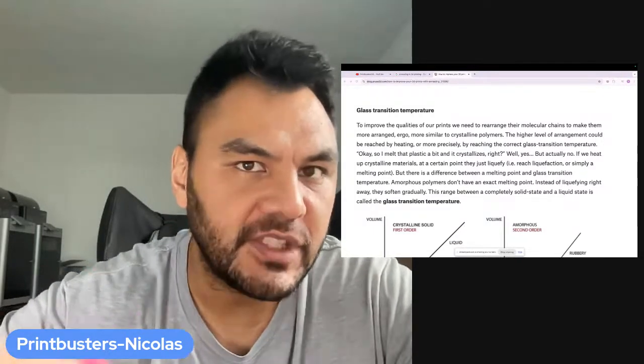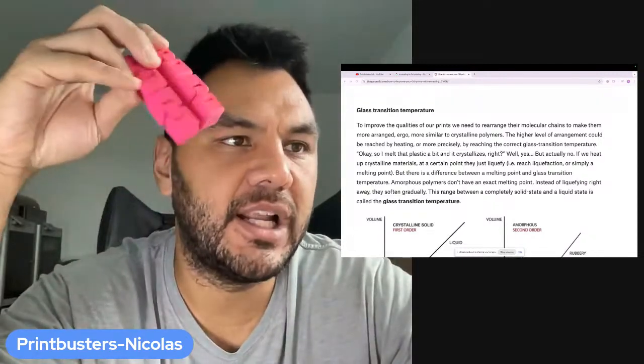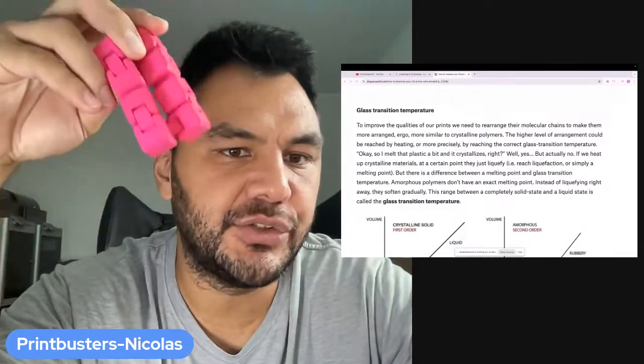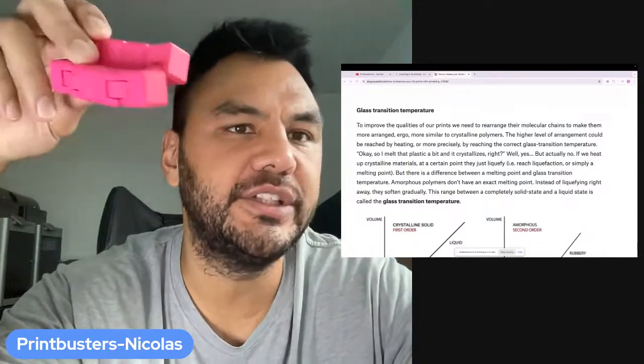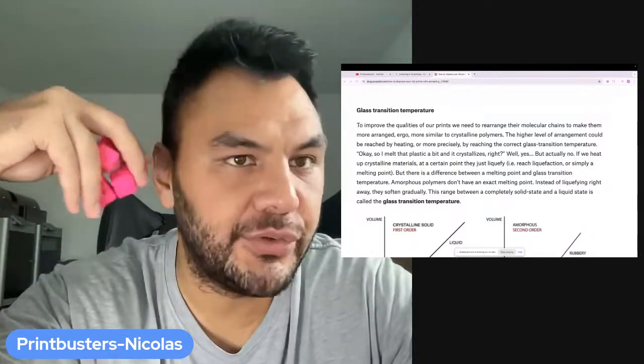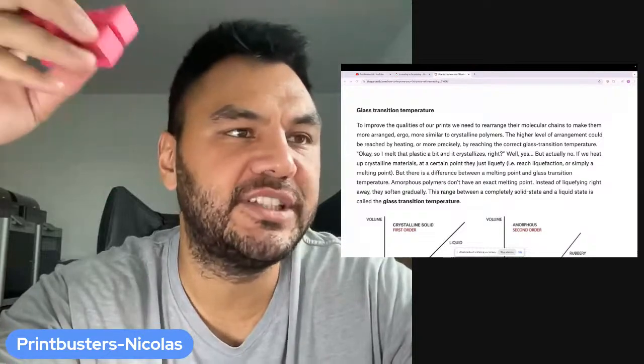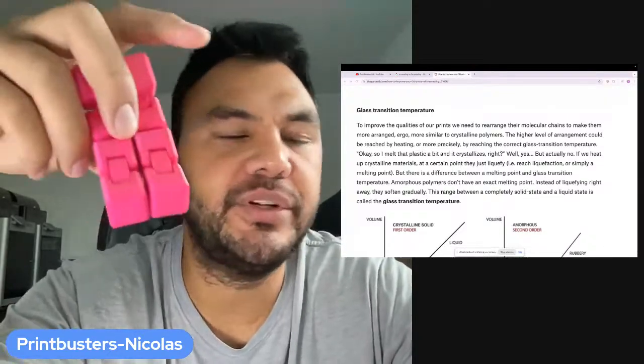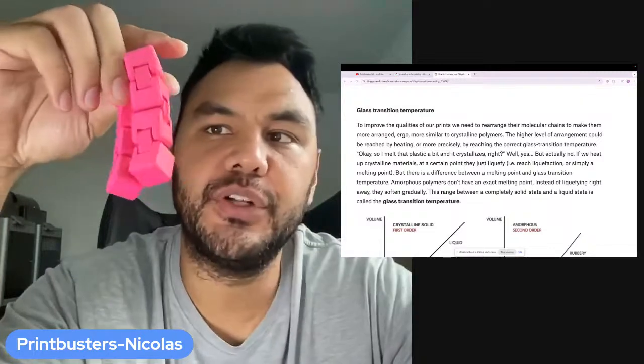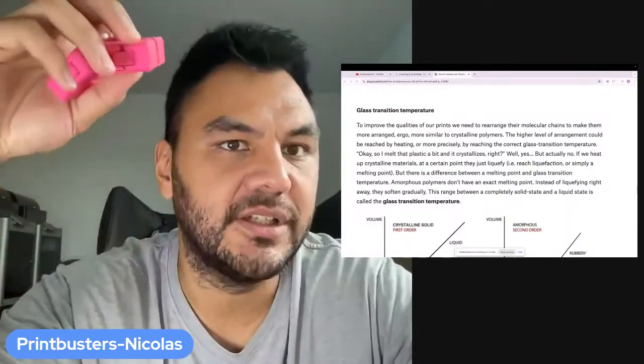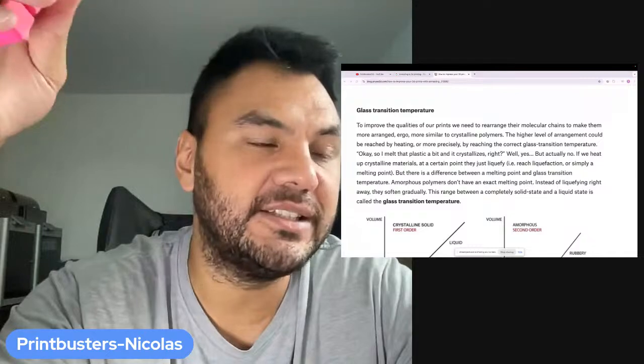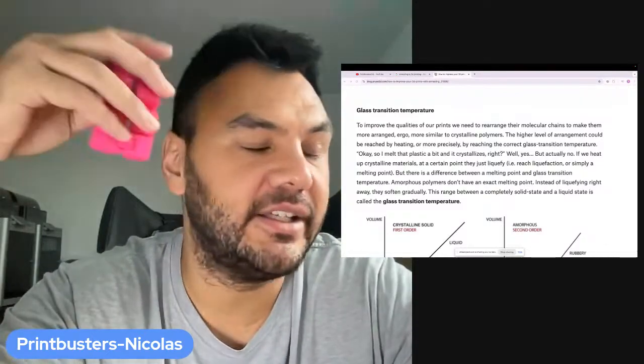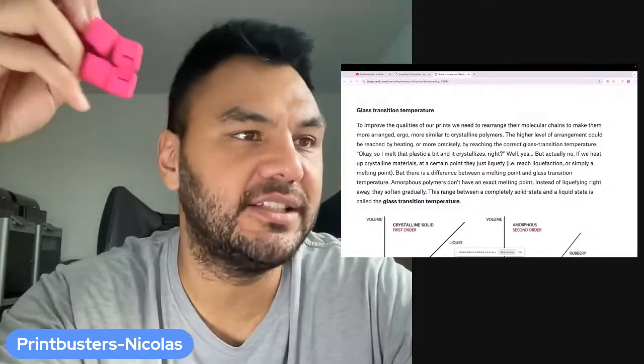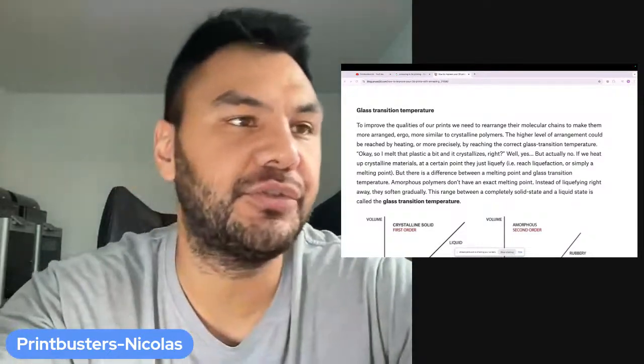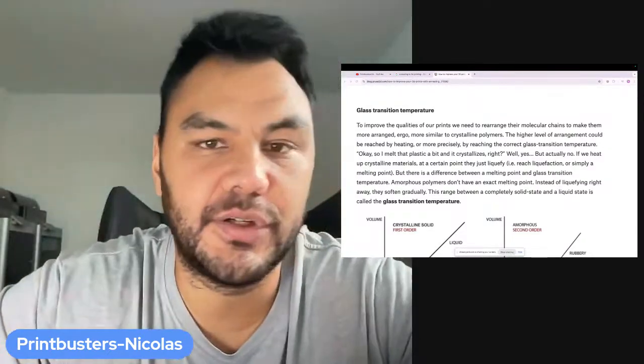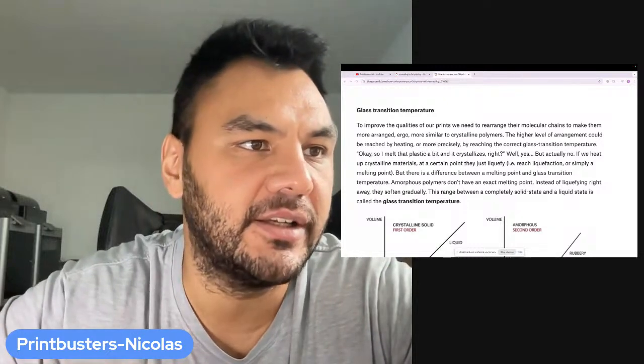Sorry, what do you mean? So basically you add some additive that will allow the crystallization rate to be faster. You increase the crystallization rate, because during the printing, usually the crystallization is not fast enough. So when you're printing PLA, it doesn't crystallize. But you can add some additives so that it crystallizes faster. But one issue of crystallizing faster is that it usually will warp, because if it crystallizes, then it's going to shrink, and if it shrinks, then it warps. So that's the pro and con, right?